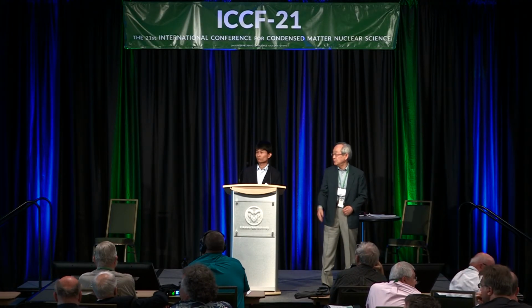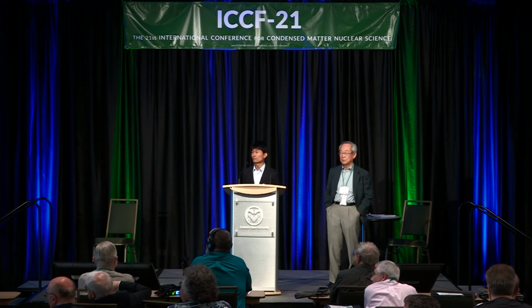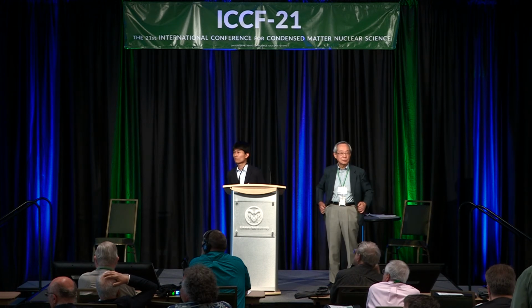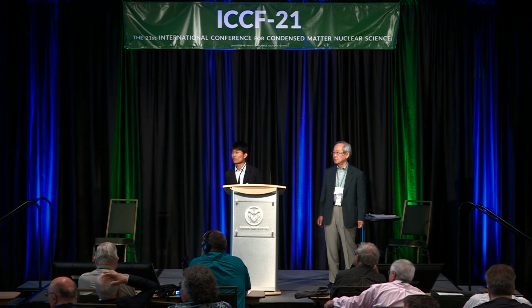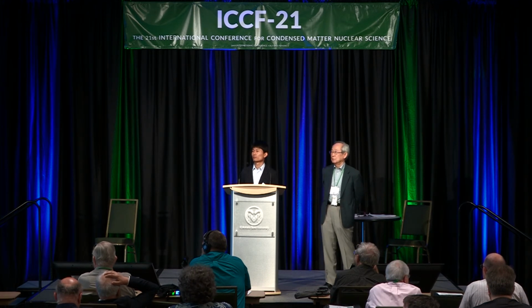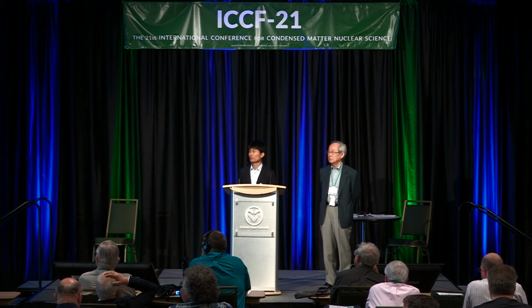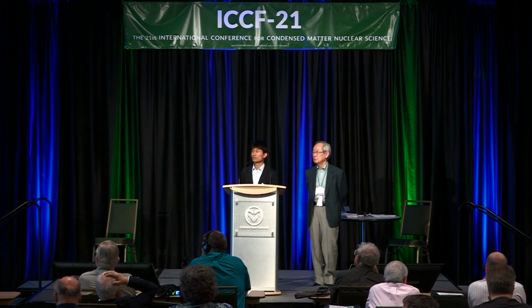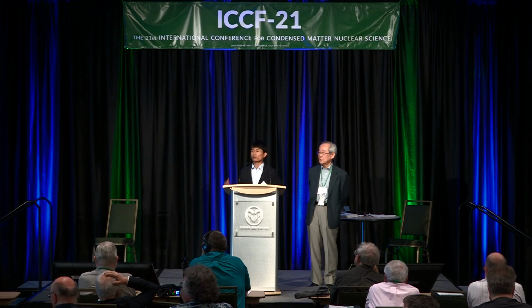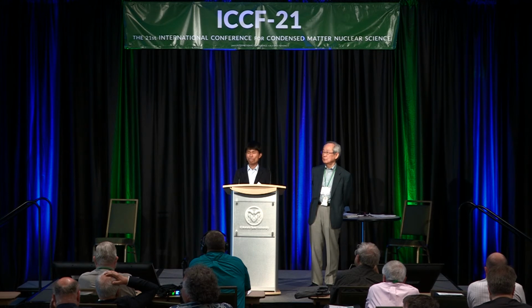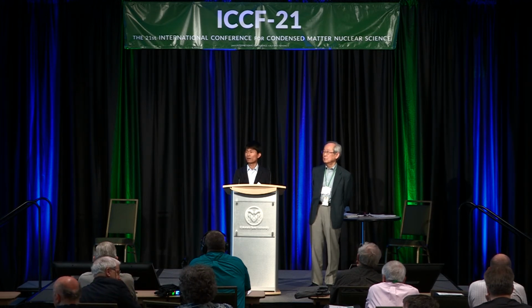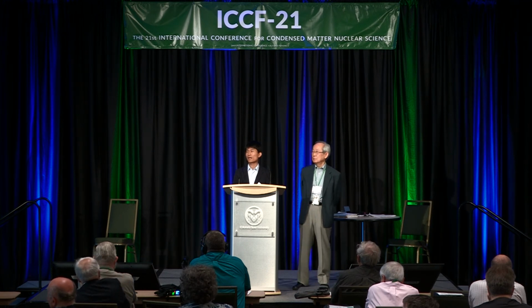Okay, thank you. When attributing neutrons to a source, it's very important to take into account that they might be originating from what's called fractofusion. Fractofusion is a way of initiating hot fusion locally in cracks. When something containing deuterium, any material actually, has cracks forming, local voltages are sufficient to produce very momentary hot fusion, and that's a very big source of neutrons. So you have to be very careful that it is not coming from that source. We also considered that, the fracture-induced acceleration of deuterons maybe. Yes, that is possible, thank you. Not yet correlated with heat.